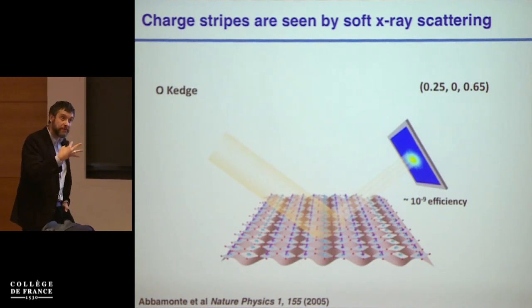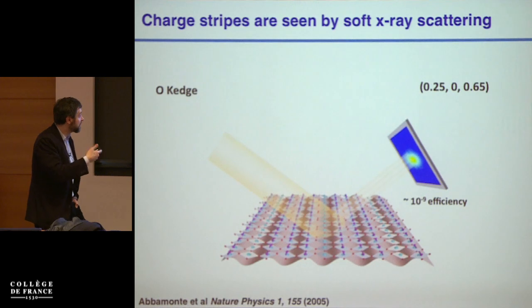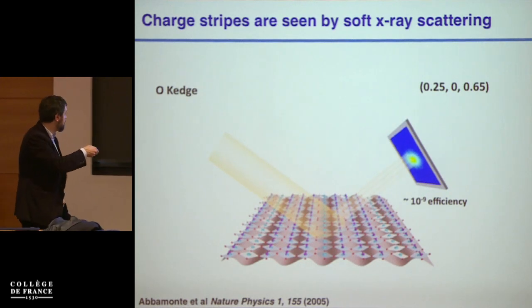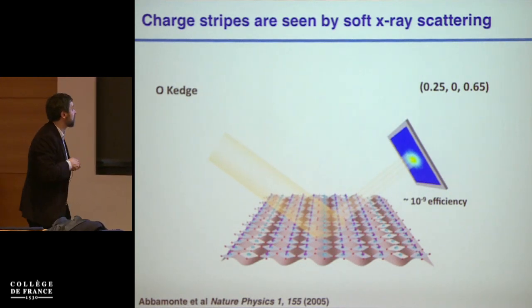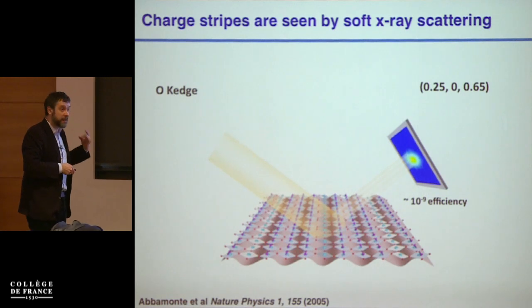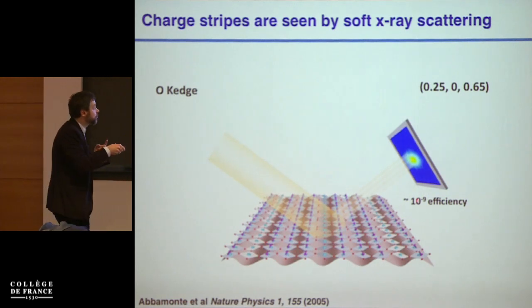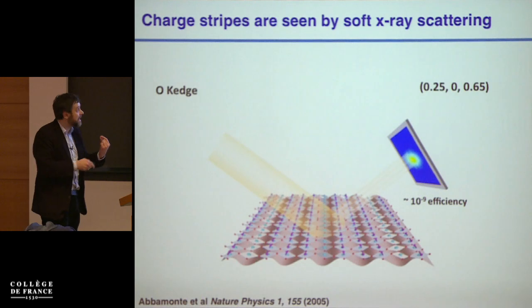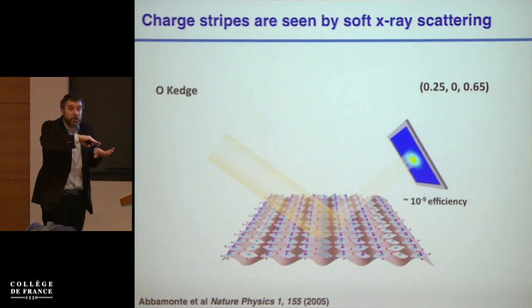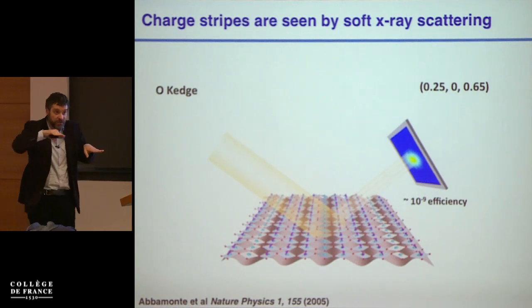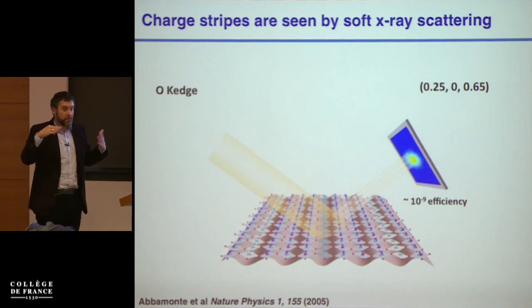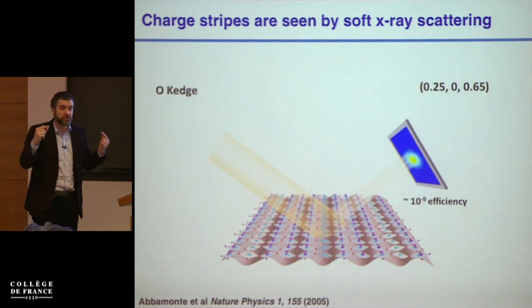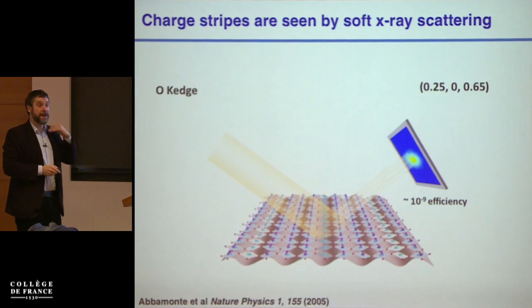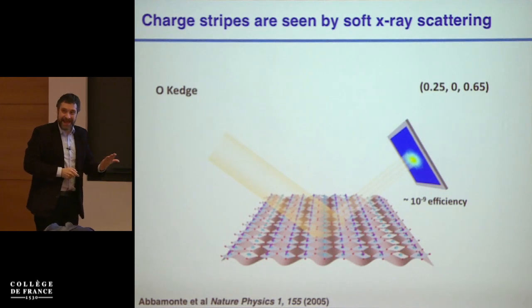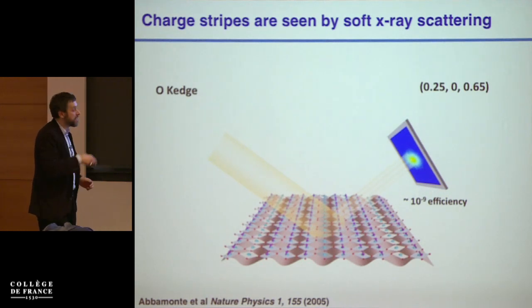This was only demonstrated at third-generation synchrotrons in the early 2000s. There's this very beautiful paper by Peter Abbamonte and George Sawatzky who saw this very clearly in LBCO by looking at this superlattice peak. One of the important things is that this is an extremely weak peak. I'm looking at a superlattice modulation of a forbidden peak by, say, 1/10 of a charge per site.